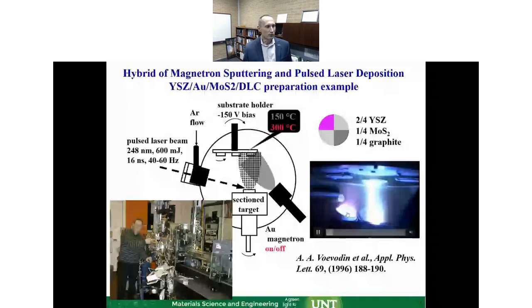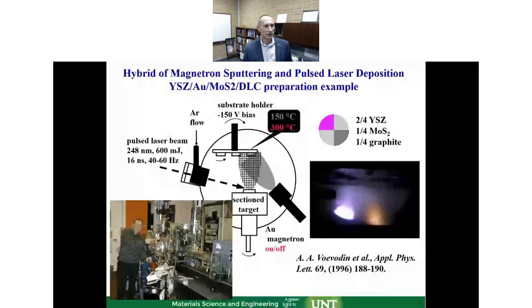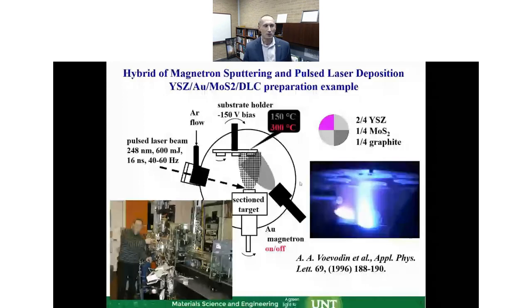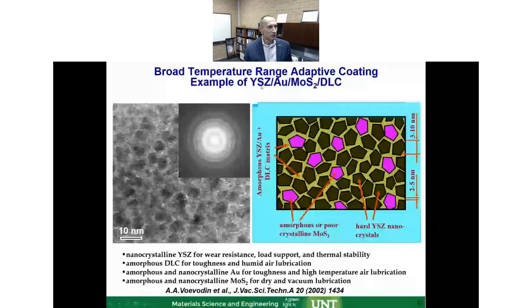Of course, in that movie what you're seeing here, you can also have multiple magnetrons, or replace the PLD with an arc evaporation source, and have all the different combinations available, and that's what we use in fact. But let me move on to what these materials can do. It comes to this type of structure, because this is an example of a zirconium oxide, gold, molybdenum disulfide, DLC coating. On the left is a TEM image. On the right is the schematic of what's going on inside of the structure.